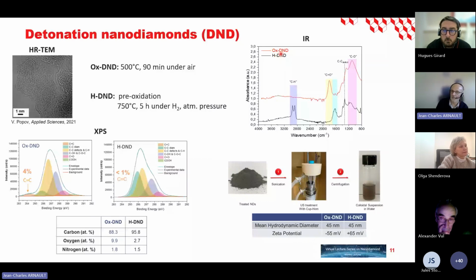related to carbon-oxygen bonds at the surface, while for hydrogenated, you strongly reduce this contribution and you have the CH signal here. Looking at the XPS, it's interesting to see that for these particles, we have a component related to defects, which is quantitatively very important. And on these particles, when you apply the hydrogenation, you reduce very strongly the oxygen concentration and also the carbon-carbon sp2 contribution from 4 to less than 1%.